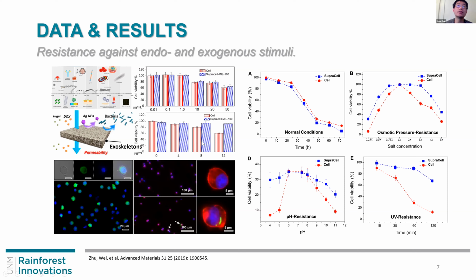But for this is the nanoparticle. Silver nanoparticle is 10 nanometers in size, and due to the selective permeability, when we increase the toxic nanoparticle concentration to 12 micrograms per ml, the SupraCells can even block them. So they were not physically attached, and not causing toxicity for the cells. And also the same for even larger ones like bacteria, for example here.